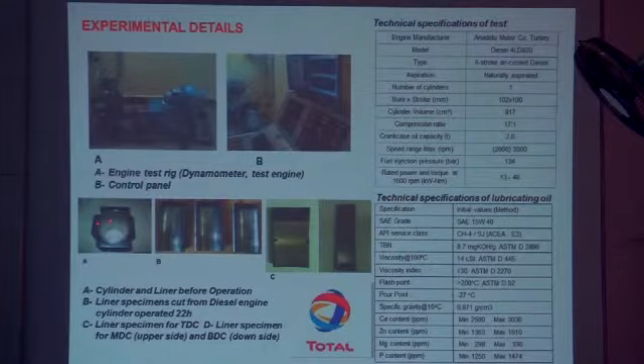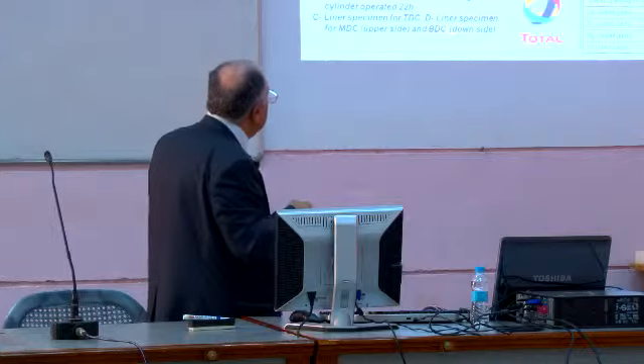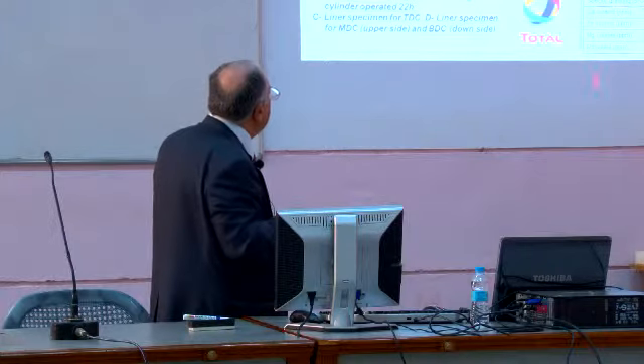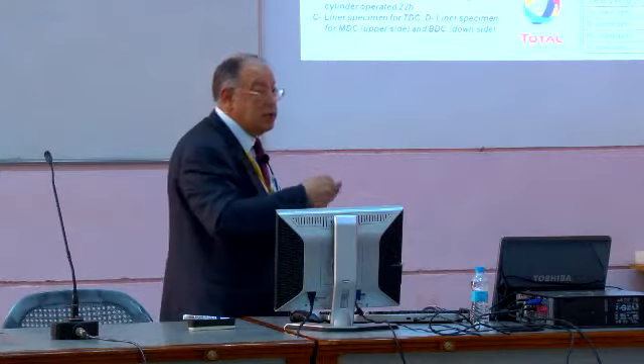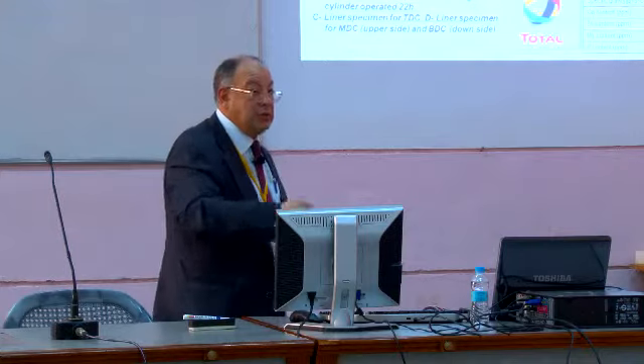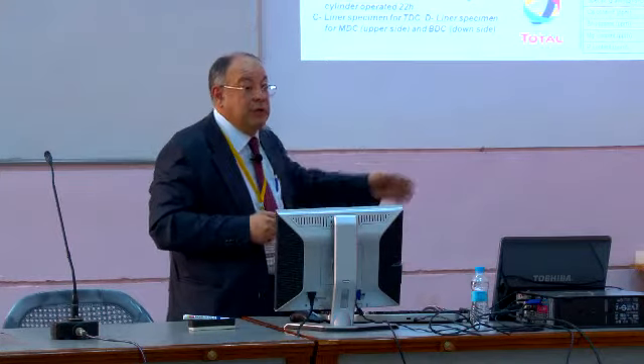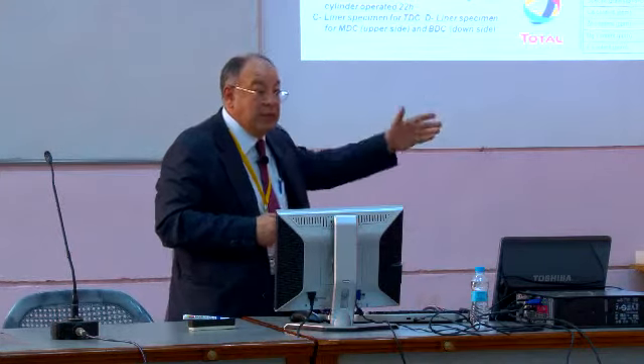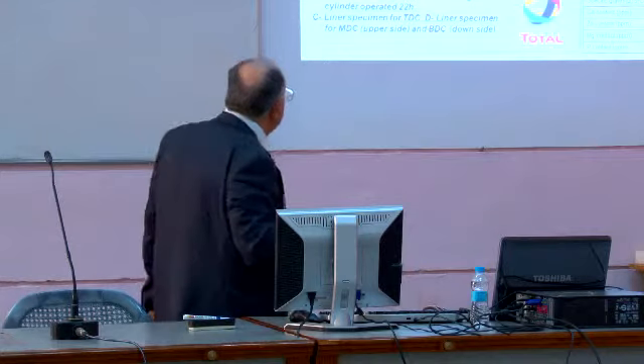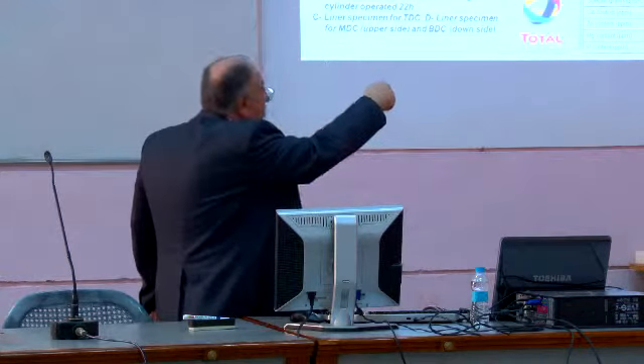And you see the cylinder liner, we cut the cylinder liner, before and after the test. The Total company supported us, so we did oil analysis and engine performance tests. We found under what conditions we must carry out the test, the operating conditions. Then we examined the surface.